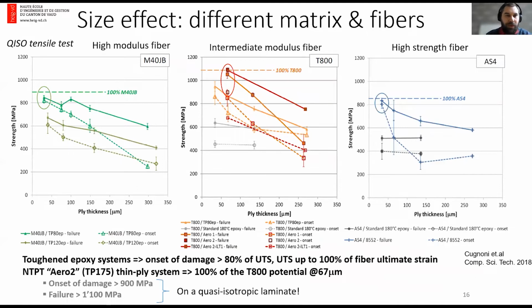We also verified this with many other composite formulations using aerospace grade resins and higher modulus fibers, lower modulus fibers, high strength fibers, many different kinds. And what is interesting is that in the best systems, by decreasing ply thickness, we could always reach a point where the onset of damage and the final failure are very close. For example, here for this T800 intermediate modulus fiber with an optimized resin system, we could reach a strength for the quasi-isotropic laminate of about 1.1 gigapascal, and an onset of damage which was higher than 1 gigapascal,